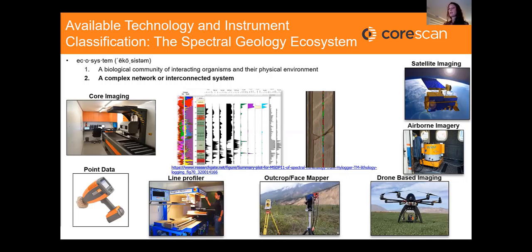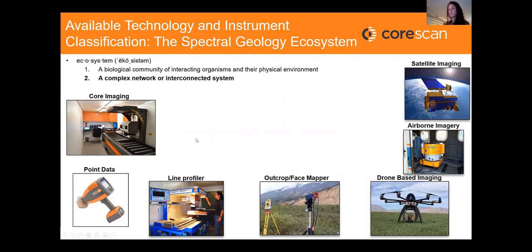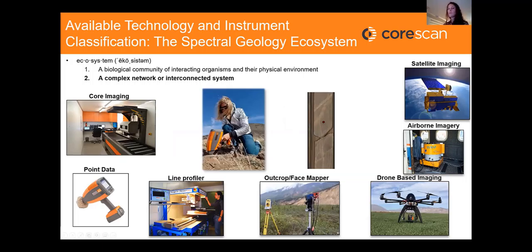We have line profiling data, where you continuously collect data down a narrow strip of your core, and that is lab-based. We have portable handheld spectrometers that acquire point data. Really, these handhelds have been around since the 90s, and they are still proving their worth today. They have a spot size of about 1 to 2 centimeters. And while they don't image your data, they can be rugged and easy to transport in the field. So there is that potential for live interpretation, just on site or in the field. They're fairly easy to use, so you can also train a technician to collect the data if that's preferred. And I believe these instruments mostly collect in the VNIR and SWIR.